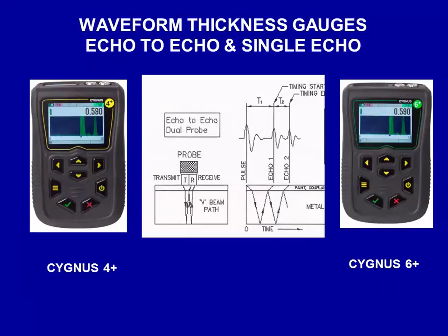Smooth it up for two purposes. One, the rougher the surface, the more sound you've got to put in it, to penetrate through the rough surface. This is, again, back to physics. The surface is so rough, you never get enough power out of the transducers to do that. So you've got to knock the surface down. The other reason you wanted to knock the surface down is that then you could do multiple echo, because our guys used multiple echo from '83 on.